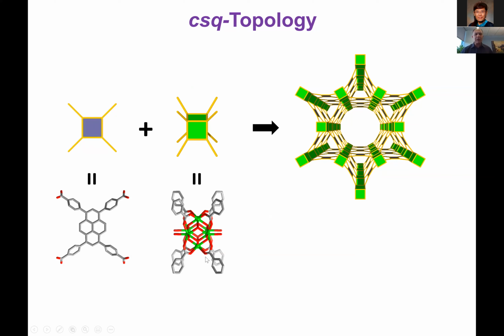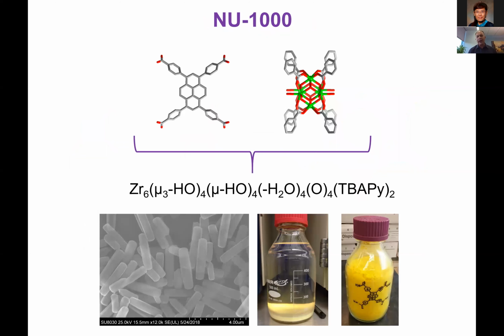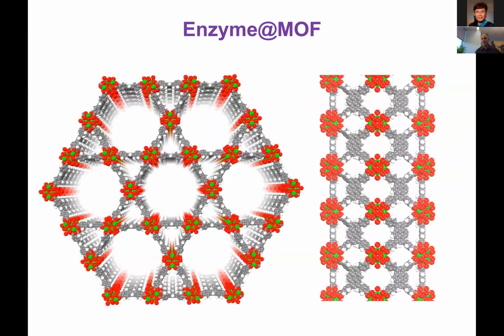A few years ago, we decided to use this pyrene tetraphenyl tetracarboxylic acid as the square because you have the 4 connectivity, and this is the 8 connected zirconium-6 cluster. If you do that, you could start getting crystals. You could see we could get the crystal structure. We could make plenty of this MOF and the ligand, and that's the crystal structure of this material.